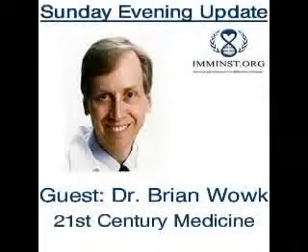There are two ways of addressing that question. There's the question of prevention, and there's the question of treatment. As far as prevention goes, preventing fractures is one of the easier problems to deal with because it's a pure physics problem. If, at least for smaller organs, you use the correct cooling protocol and storage temperature, you can avoid fractures. In fact, I myself have managed to cool rabbit kidneys all the way down to liquid nitrogen temperature, keep them submerged for 2 weeks under liquid nitrogen, and then rewarm them with no fractures whatsoever if the correct cooling and warming protocols are followed.